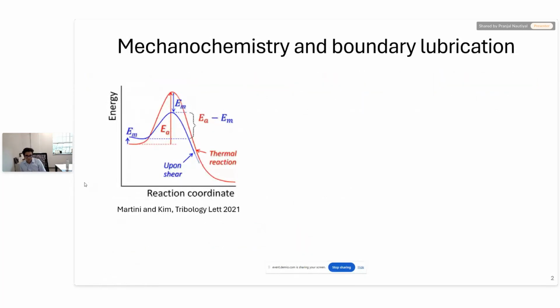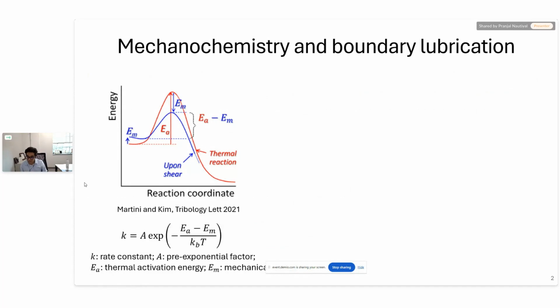So traditionally, when we look at chemical reactions, we start with reactants, which are in a state of local equilibrium, and we provide energy, which is typically heat. This helps reactants cross an energy barrier to form a product. Now, when mechanical stresses are introduced into the reaction system, that reduces the effective energy barrier required for the chemical reaction to proceed.